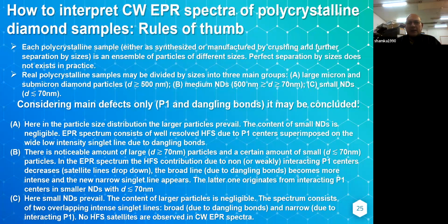Perfect separation by sizes doesn't exist in practice. Real polycrystalline samples may be divided by sizes into three main groups. Group A, large micron and submicron diamond particles with a size above half micrometer or 500 nanometers. Group B, medium nanodiamonds with sizes between 500 nanometers and 70 nanometers. And small nanodiamonds with sizes below 70 nanometers.